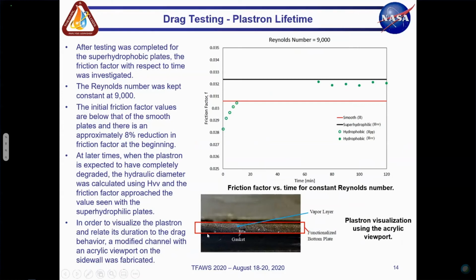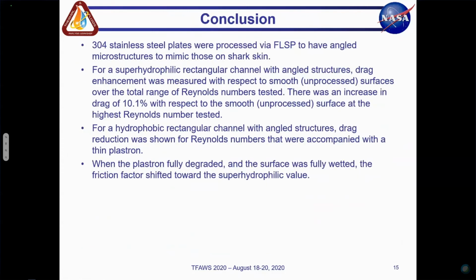And then we modified the channel to get a little acrylic viewport so that we can watch this plastron degrade over time. And it's a little difficult to see here, but you are able to see somewhat of an air layer that is present in this hydrophobic channel.